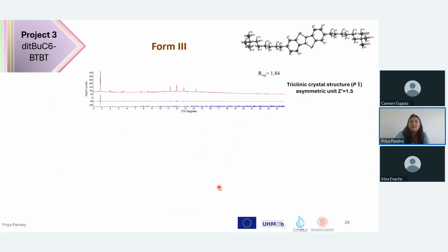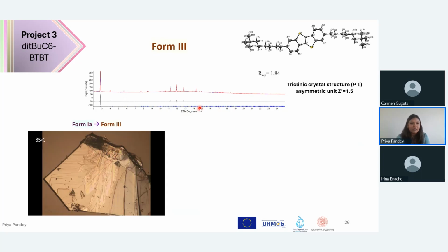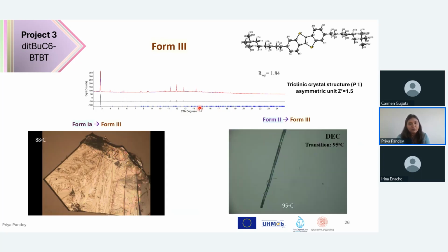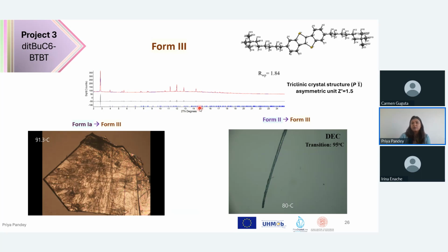In the end, we always have a high temperature polymorph. So I indexed it again using TOPAS, it being disordered at high temperature. And both form 1A and form 2 crystals transform to form 3 at high temperatures.